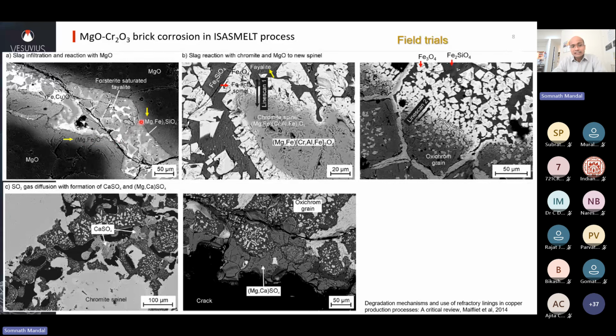The slag also leaches out magnesia, and fayalite is basically Fe2SiO4, right? And then the slag gets enriched in magnesium that is coming out by leaching the refractory, and it forms more and more magnesia-enriched olivine, which is a solid solution of fayalite and forsterite. And then in the chromite grains, you see the periphery is getting reacted and forming magnetite, Fe3O4. So this is the slow dissolution process.